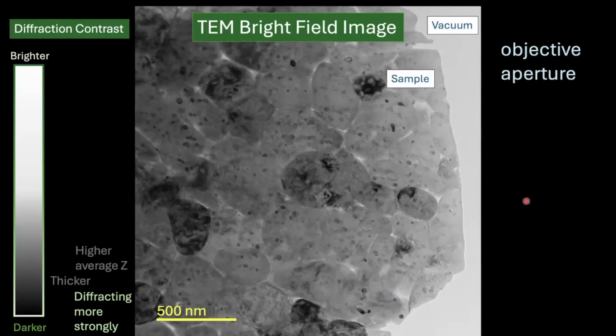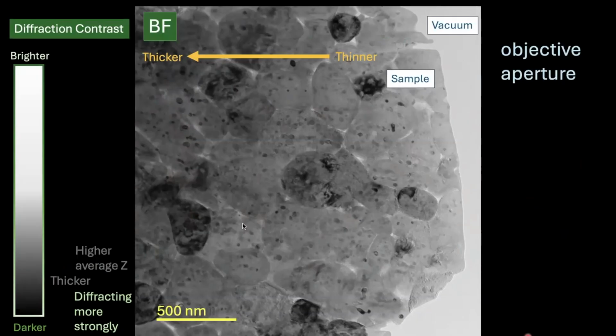And then the objective aperture is in here. That's just to give it more contrast. So you can see it gets darker towards the left because it's thicker. So there definitely is contribution from all of those factors. It's just mostly from diffraction. So whenever I show one of these images, I'm going to keep this whole bar there on the left because I will be showing bright field images and dark field images, and that can get confusing.